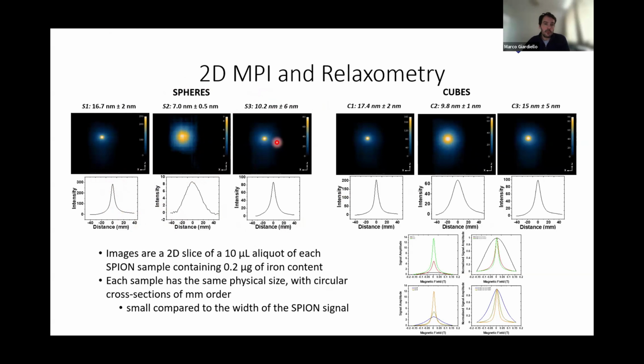What was interesting was, although these were very polydispersed, clearly the larger particle has a dominant effect on your signal, because that contains both this and this, but you're still seeing quite a nicely resolved image. And this is just the same data plotted as a normalized curve, so that you can see the resolutions of difference. So that's what we are starting to look at.